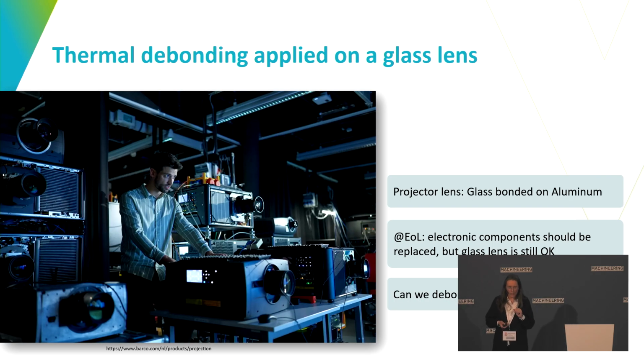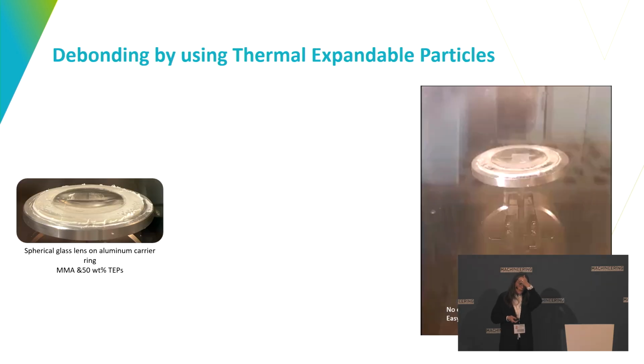So when we come to some examples, our first example that I want to show you is thermal debonding on a glass lens demonstrator. For example, you have these projector lenses, and at end of lifetime, quite often these electronic components are really end of life and going to a waste stream, but your glass components are of higher value and can be reused. They're not damaged yet, they can just be reused. So it would be good to see if there is a possibility to use reversible bonding in this example. Therefore we made a demonstrator based on a spherical glass, so it's not a flat glass, glued on an aluminum carrier. And we use MMA adhesive together with these TEPs.